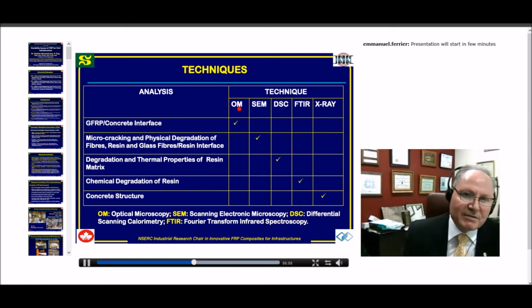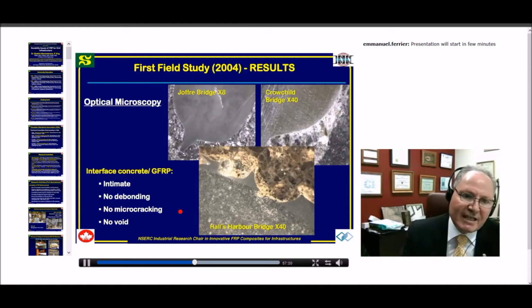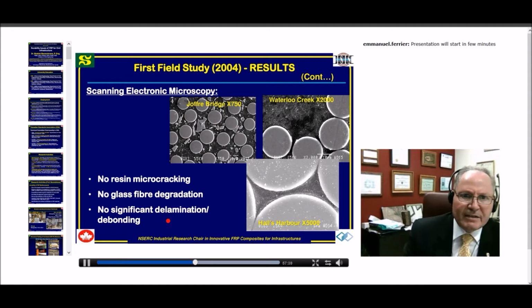We looked at the GFRP-concrete interface by using optical microscopy, microcracking, and physical degradation of the fiber, resin, and the glass and resin interface by SEM analysis, degradation of thermal properties by DSC, chemical degradation of resin by infrared, and concrete structure by X-ray diffraction. We also did EDX, which I'm not showing here, and many other analyses. Here are some slides showing the optical microscopy near the interface. Here showing 3 different structures, and we can see the interface is intact, with no debonding, no microcracks, and no voids in the GFRP.